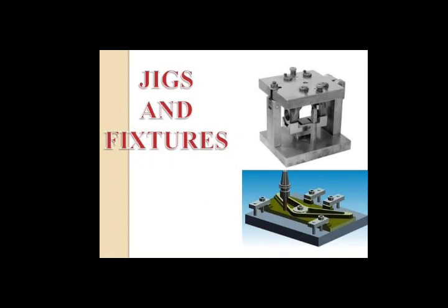Now when we consider this, we have to go again to the drill bushes. Now what are the drill bushes? They are used to guide drills, reamers and other tools to the required position on the workpieces. Drill bushes are water hardening carbon steels having 0.85 to 1% carbon or 0.75 to 0.9% manganese, which is hardened to RC64 to increase wear resistance.